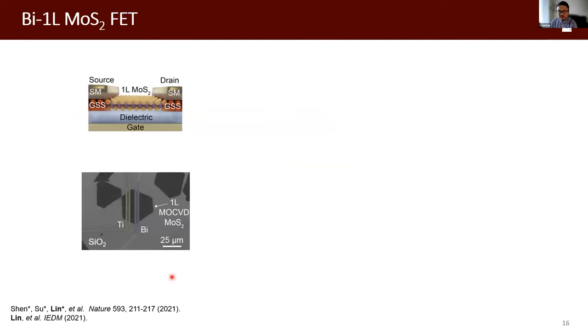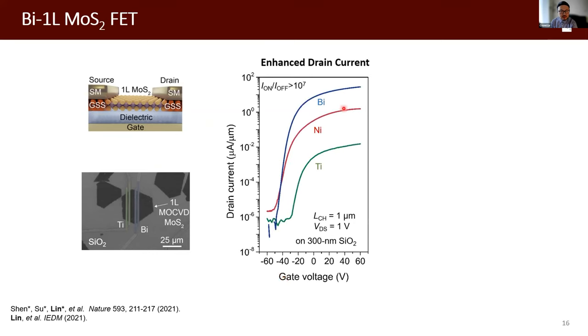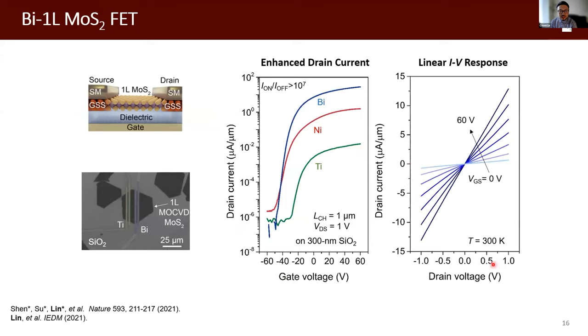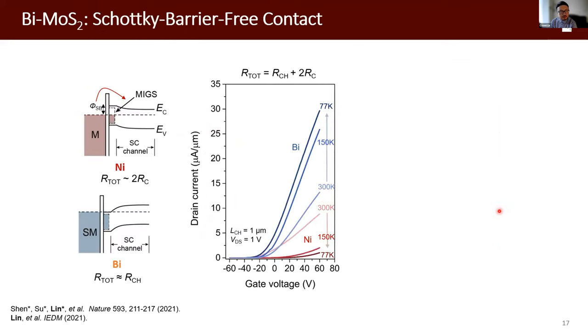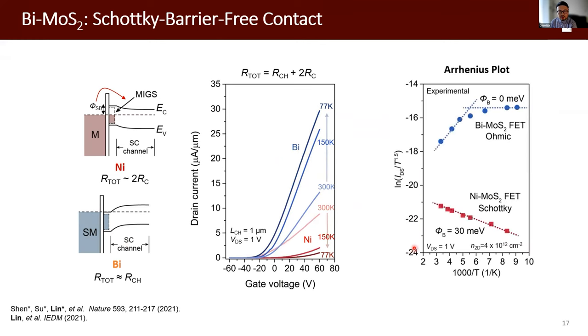Now let's fabricate devices to see if it indeed gives us a good contact resistance and good device performance. We fabricated different metal contacts with our MoS2 and made a transistor structure. As we can see, bismuth shows an order of magnitude better current response with respect to our baseline metal. From the drain current versus drain voltage, the linear response also indicates there isn't any energy barrier formed at the interface. To better understand the band alignment, we can conduct temperature-dependent measurements. As we can immediately see, the bismuth contact has the opposite temperature dependence to the conventional nickel contact, for example. And from this, we can replot it into the Arrhenius plot.